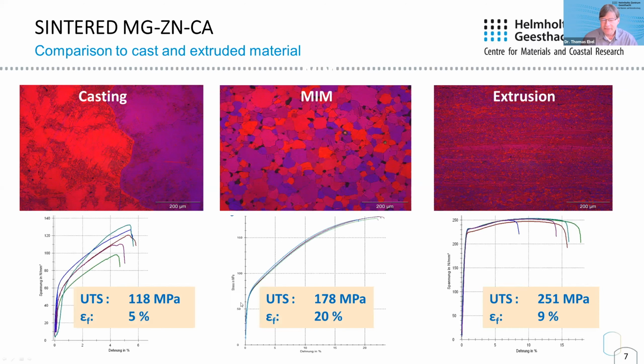So the UTS is somewhere between the cast and the extruded material, typically, but this is UTS. If you compare yield strength, you can see that there's nearly no difference between casting and MIM. So the extruded material is simply a very good one. That's no question.